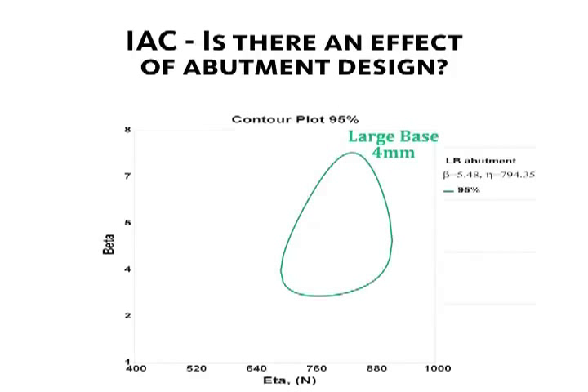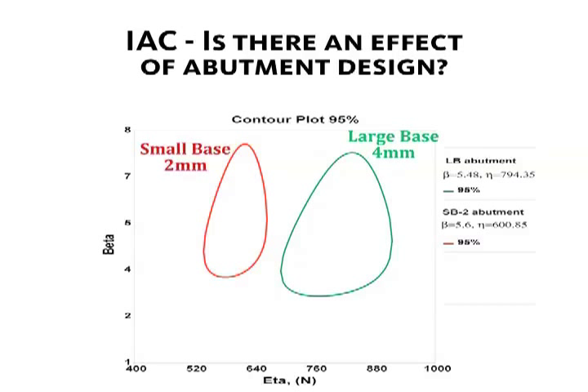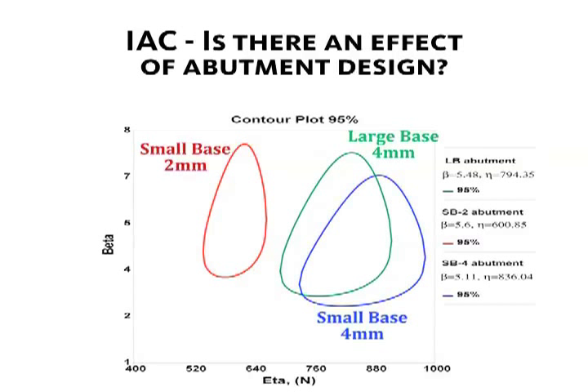Just like the graphic we have seen in the previous investigation, the positioning of the contours showed that the large base abutment was significantly stronger than the small base with a 2 mm post. However, the reduced base on a 4 mm post resulted in similar strength to the large base, as we may see from the overlapping between these two contours.